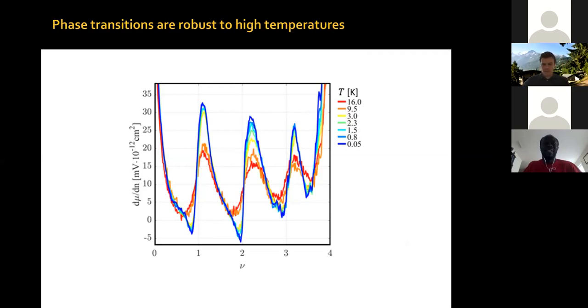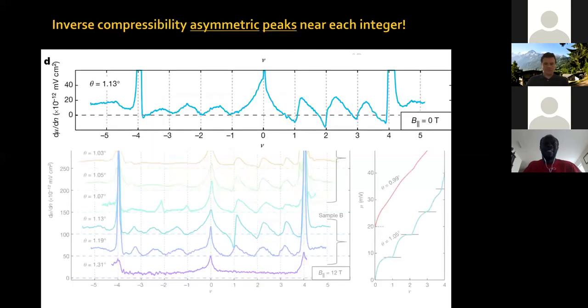Sure. So it looks like, based on your presentation, you have inhomogeneity of the magic angle in your sample. We have inhomogeneity of the twist angle. Yes. Yeah. So of the twist angle. Sorry for the mistake. Now, depending on what that twist angle is, how the incompressibility varies as a function of filling factor looks quite different. So how did you determine a priori that this is the twist angle that you have, if this plot is quite complicated depending on what the twist angle is? Yeah, very good.